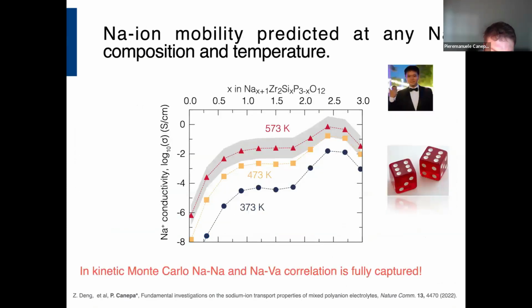And we use this model to drive kinetic Monte Carlo. What kinetic Monte Carlo enables us to do is that we can measure the conductivity at various temperatures, indicated by different color lines here, and at different compositions. So what comes out here is that at composition 2.4, meaning that you have 3.4 sodium per formula unit, you have a peak of ionic conductivity. As you decrease the sodium content and you go to x equals 0, meaning 1 sodium per formula unit, the conductivity tanks, and this is well aligned with phenomenological experiments.